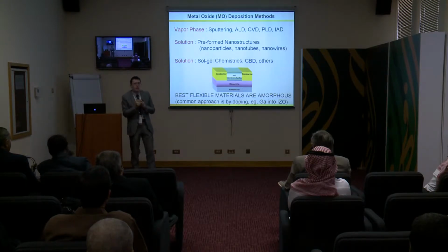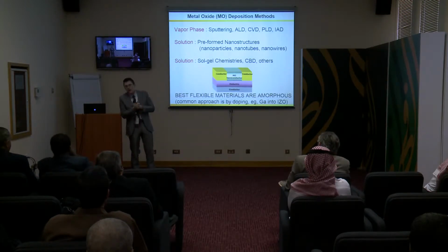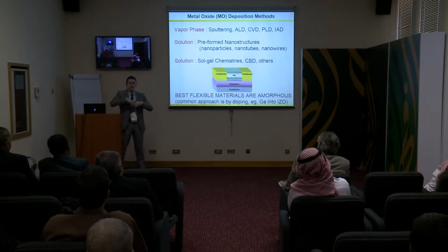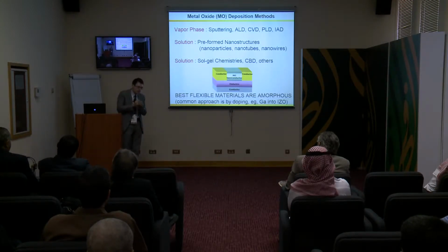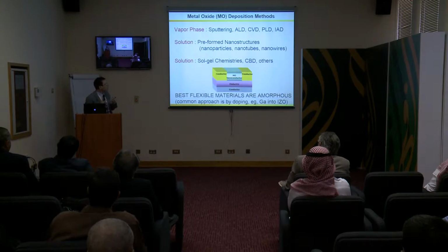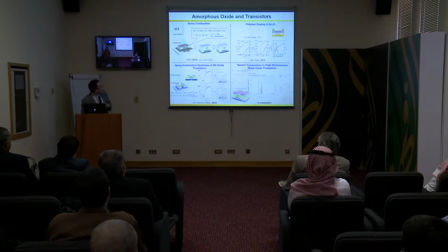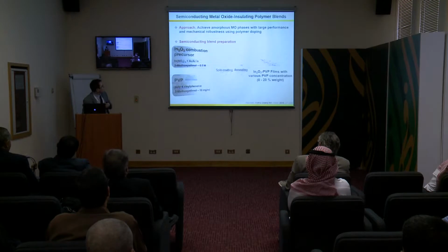The more conventional approach is you start from a matrix, which could be indium based, for example, indium oxide, or zinc based, zinc oxide, and then you start adding elements. So you add gallium, you add a little bit of zinc, a little bit of tin, and when you have more elements, because of the difference in the geometrical dimension and the coordination chemistry, the lattice gets confused, so you get amorphous phases much more effectively. So this is the typical way to make amorphous phase. And we have shown some results on this.